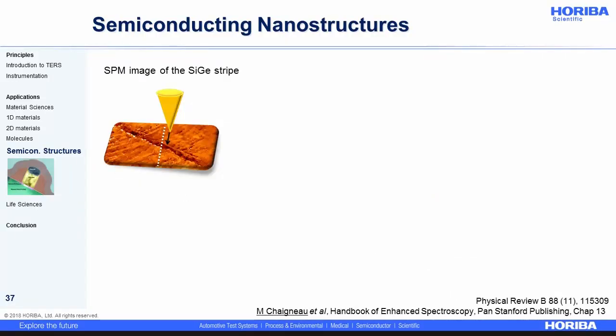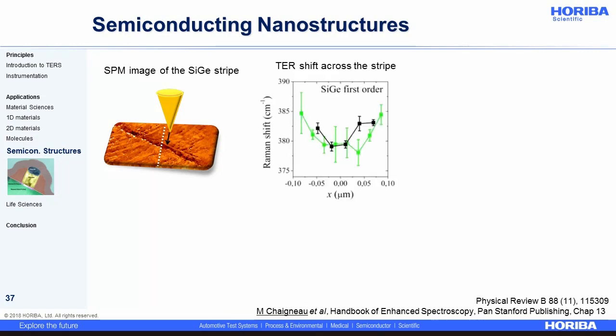So how have we done the measurement? First of all, we use, as usual, the TERS tip for a pure SPM image of the silicon germanium nanostripe, as you can see here. And through one single line, we perform a TERS profile in order to monitor not only the Raman intensity but, in this example, the Raman shift across the stripe. And you can see a huge shift in the Raman band position of the silicon germanium mode from 385 to 380 centimeters minus 1 from the edges to the center of the stripe.